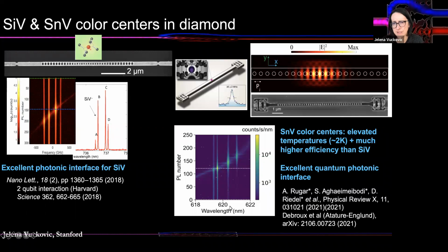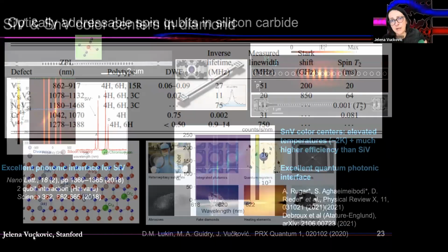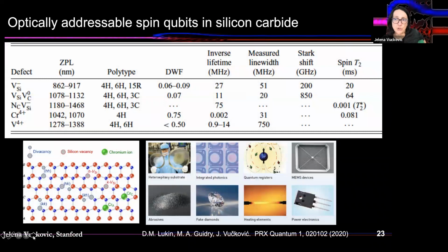And recently we demonstrated an excellent quantum photonic interface for this. I'll say a few words about that in a moment. And then in collaboration between the groups of Mete Atatüre in Cambridge and Dirk Englund at MIT, they've also demonstrated optical spin control and excellent spin properties of these qubits, putting them on par with silicon vacancies and proving that indeed their properties are exactly the same, but at elevated temperatures, which is actually very important for these experiments. So dilution refrigerators are not needed for tin vacancies.